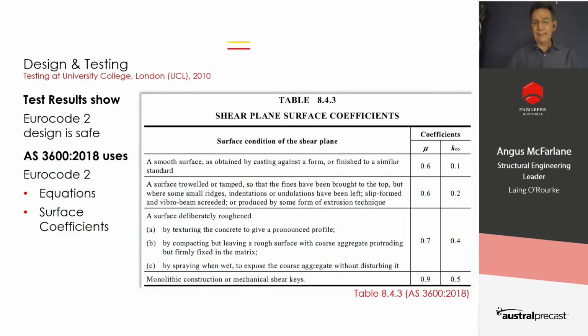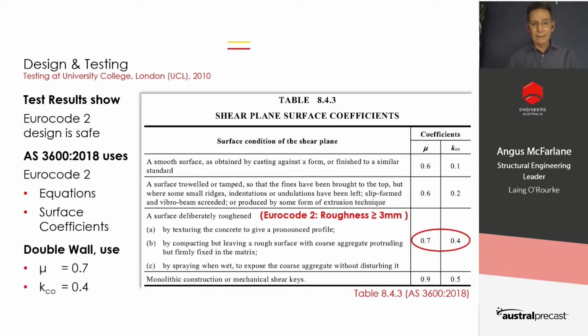Now, the reason for this testing and why it's applicable to Australia is the Australian Concrete Code, AS 3600, uses the Eurocode 2 equations. It's the 2018 version. So you can see that there in table 8.4.3. Now, AS 3600 doesn't explain the roughness very well, so I've put in what the roughness from the Eurocode is, 3 millimeters. I think the roughness would probably come out in a commentary to the code, which I haven't seen yet.